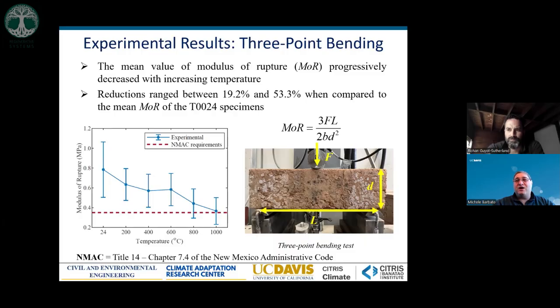And so actually our conclusion was that we used too much cement. We could have had a better performance by using a little bit less cement than what we used, which I guess is good for optimizing these blocks in the future. But from the modulus of rupture, we have this slight decrease in the performance, which is still above the minimum requirement for the New Mexico Administrative Code.